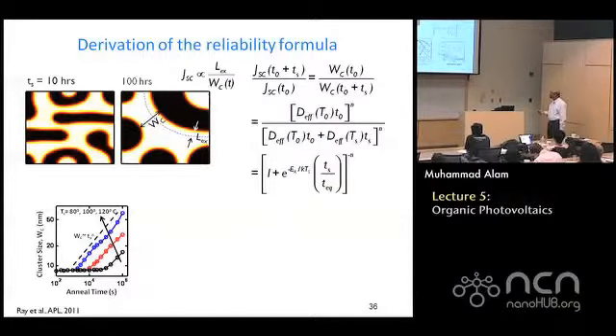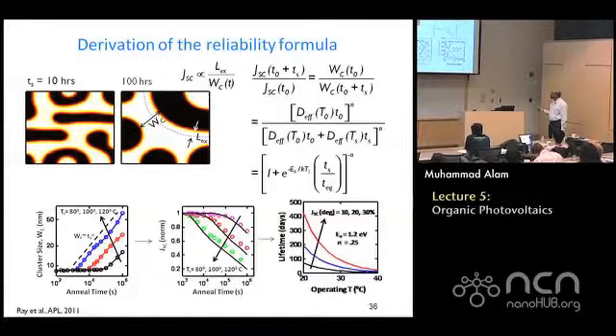And so what's going to happen? Your short circuit current is going to fall, and these are experimental data, and this is the theory that says that generally the trend is pretty well reproduced. And how much is this? This is in seconds. So this is a couple of hours, and most things die within a month. So this is the reason why this happens, and you can calculate the lifetime. You'll be lucky if you get 1 or 2 years. So that's how this thing works.